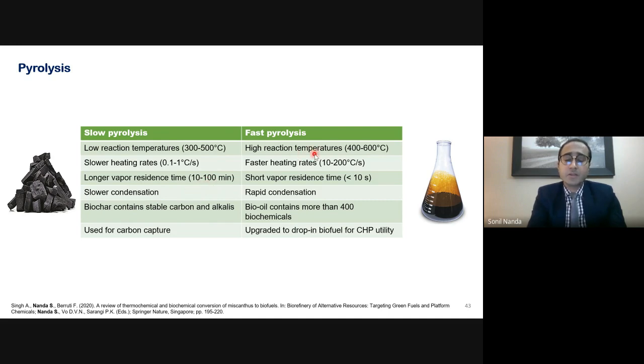Now, in fast pyrolysis, high reaction temperatures are involved, for example, 400 to 600 degrees Celsius. Faster heating rates ranging from 10 to 200 degrees Celsius per second are involved, whereas the vapor residence time is extremely short, less than 10 seconds, which means that the biomass is cooked under an inert atmosphere, mostly generated in pyrolysis with the application of nitrogen gas.